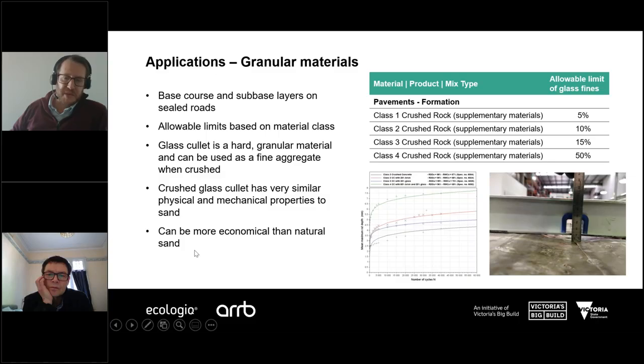So we've actually been undertaking quite a bit of work at ARRB recently, looking at the performance of various granular blends for both sub-base and base courses, and assessing those under our extra large wheel tracking facility, and comparing them with typically used natural aggregate and recycled crushed concrete, and even including potentially 20% recycled crushed glass, even in cooperation with 20% recycled crushed brick. We're still seeing that these materials are performing adequately for certain locations within our pavement structure.